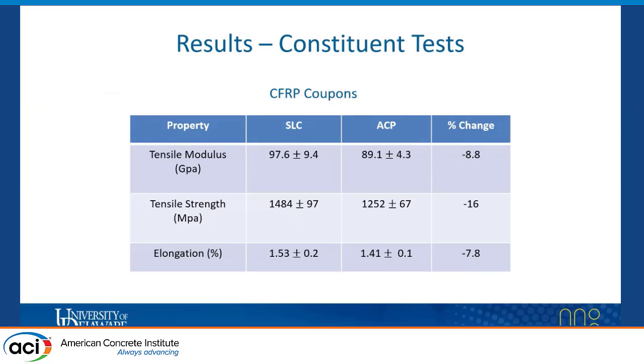Now we'll move into the results from the testing, starting with constituent tests. It was found that between the SLC and ACP CFRP coupons, the decrease in tensile modulus as well as the decrease in elongation was statistically insignificant. However, the decrease in tensile strength amounting to 16% was statistically significant. What's interesting to point out about this decrease of 16% is that it's in line with the environmental reduction factor suggested by ACI 440.2R for exterior exposure to CFRP, for which ACI recommends a reduction factor of 0.85.